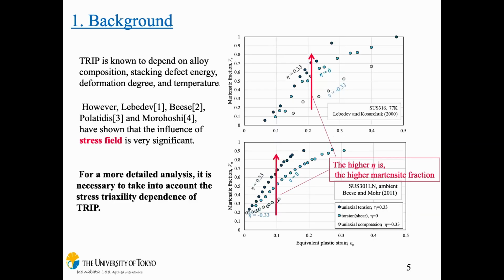And TRIP is known to depend on some factors such as the temperature and the composition and so on. However, these four researchers have shown that the influence of the stress field is also significant. This graph shows the martensite volume fraction, and we can see that when the stress triaxiality becomes higher, the martensite volume fraction also increases. But in the conventional elastoplastic FEM, the stress triaxiality dependency of TRIP is not considered. So, for more detailed analysis, TRIP should be considered.